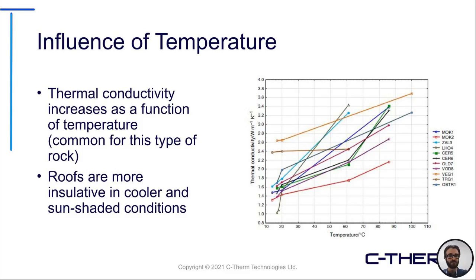Next, as I mentioned, they were also looking at how those samples fared under the influence of varying temperature. And we can see from the graph, there's an overall trend here. Generally, the thermal conductivity increased as a function of increasing temperature, and this is common for this class of rock material. But obviously, this does have some bearing on the end-use application. So whether the roofs were in a shaded area or exposed to the open sun in non-shaded areas, these different materials can have different performances based on the temperature that you're subjecting them to, which will in turn influence their insulative performance as a roofing material.